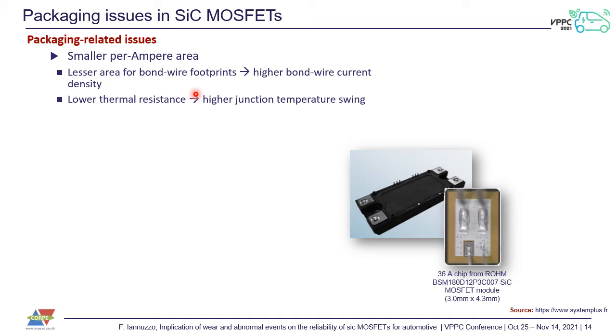And the second is that because of the lower intrinsic thermal resistance of the material, which is good, of course, the thermal time constants are smaller, or thermal transients are faster, and basically with the same electrical stimulus, you have a larger temperature swing. In this picture, you can see a detail of a single chip or a multi-chip module produced by Rohm. You can see that because of the limited area, only 2 bond wires can be put on the chip top on the source side. This is, by the way, a 36 ampere chip, so the current per bond wire is up to 18 amperes.